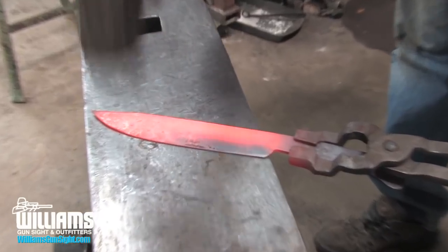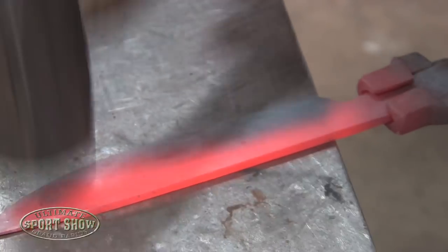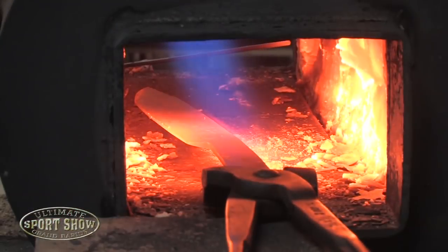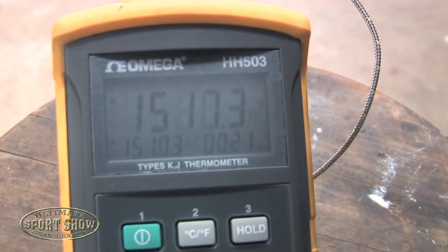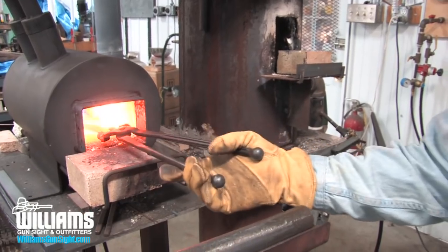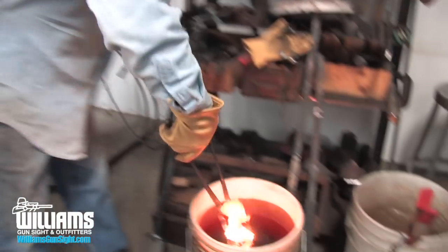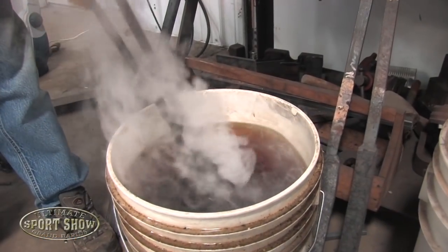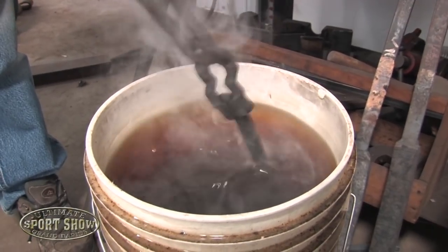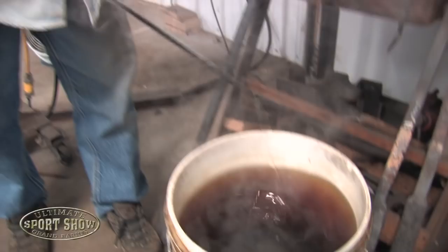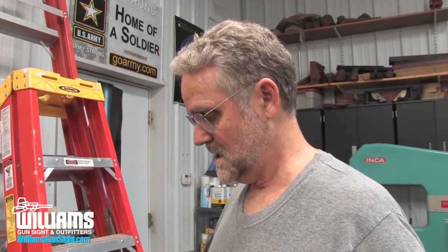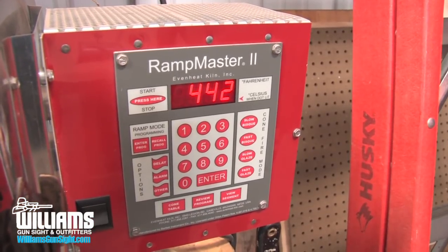the steel and we've made the blade, in order for the knife to become a good cutting tool, it has to hold an edge. At first, we go through the hardening process, which is heating it up to 1500 degrees and then quenching in oil. Then it is completely hard, but it is too hard at that point. It's like glass. It's susceptible to breakage and to cracking. And in order to prevent that, we put it into a heat treating oven, or it can be your own home oven actually, and different temperatures will lower and soften the steel just a little bit, but enough that it's tough and it will hold an edge. In other words, it won't crack. It'll be a good using tool then. And that's what the tempering cycle is all about.